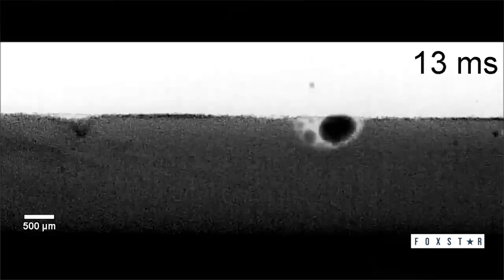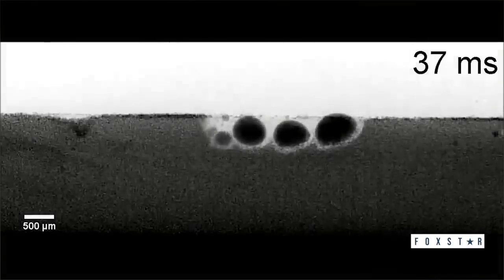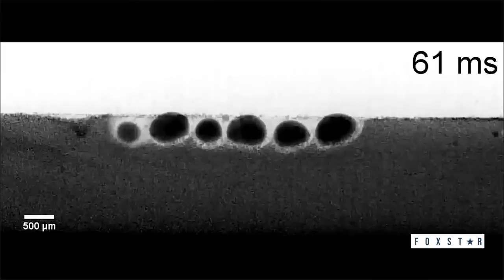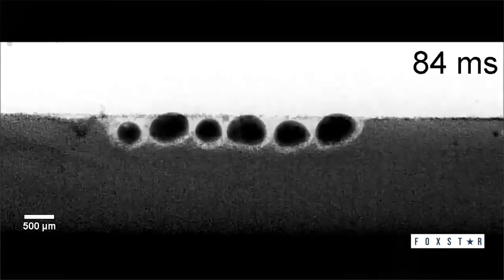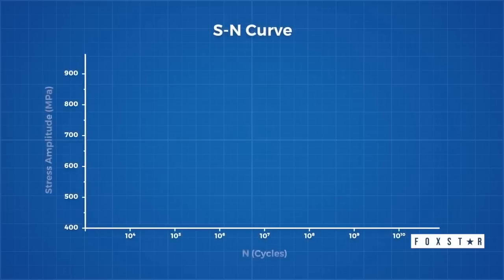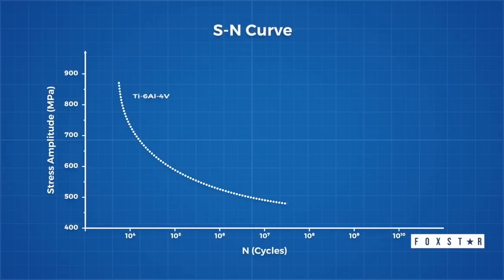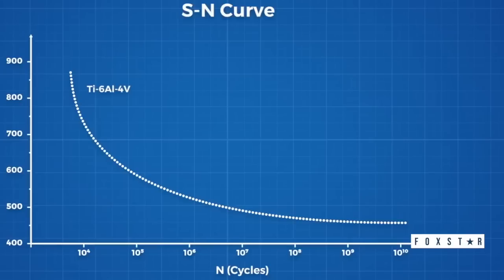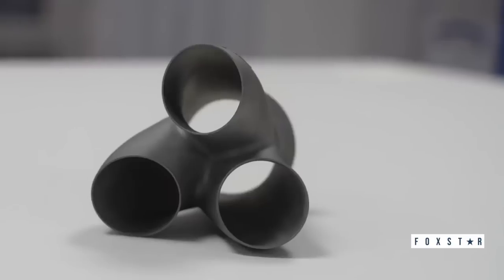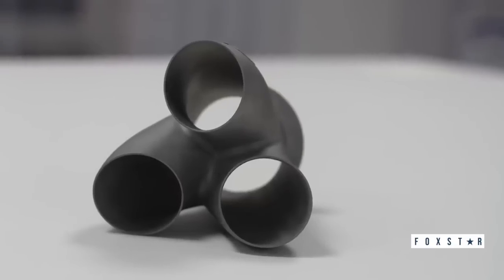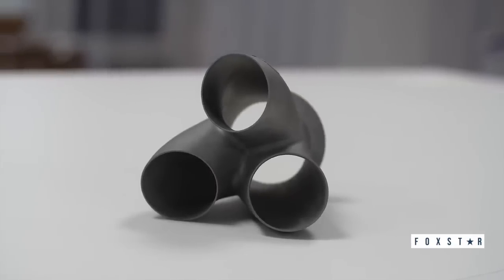This creates parts with a lot of micro imperfections, and imperfections lead to decreased life as fatigue causes cracks to form. We can visualize a material's fatigue strength by plotting on an SN curve, which places the magnitude of the alternating stress on the y-axis and the number of cycles it survived on the x-axis. For traditional machined titanium, it looks something like this, whereas for 3D printed parts, it looks like this. 3D printed parts simply fail much sooner because of these tiny imperfections.